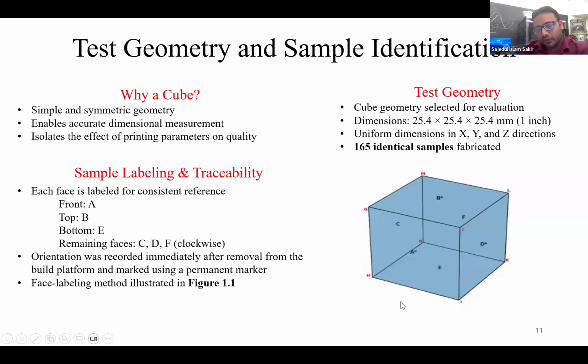Then we labeled all six surfaces of the cube: front face A, top face B, bottom face E, and the remaining faces in the clockwise direction C, D, F. After printing and immediate removal, we take a permanent marker and mark all of the faces for identification. The cube dimension we used is 1 inch, uniform, and we printed 165 identical samples in this printer.